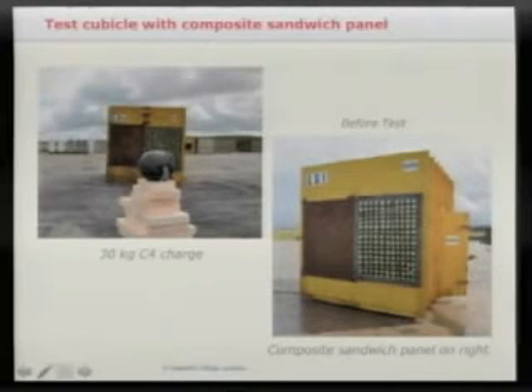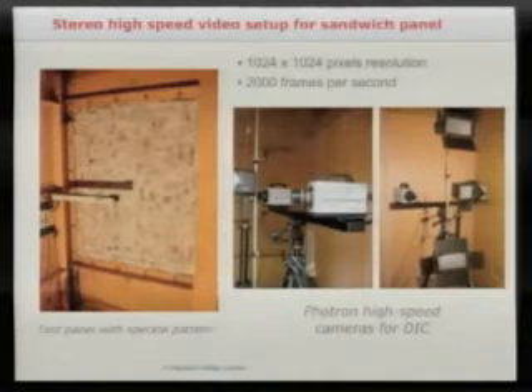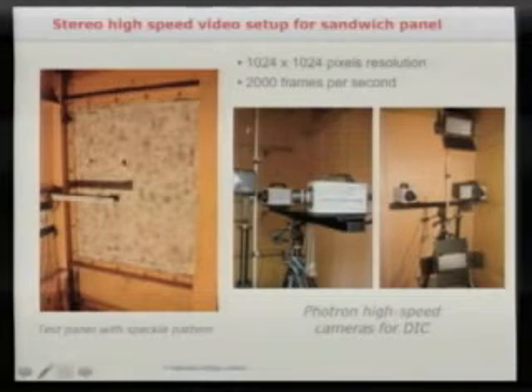We put a series of lines, so we've got a camera at the front which can photograph what's going on. But what we're really interested in is what's going on the back of the sample. And there you can see the speckle pattern. In the early days when we did this, there was a little bit of suspicion about whether we were going to get accurate data. And so we also have a laser gauge, which is a cantilever with a laser on its end, just to give an independent measurement. And there we have the two high-speed cameras, as you saw before.